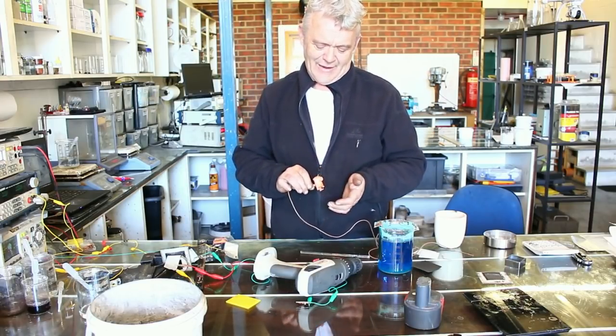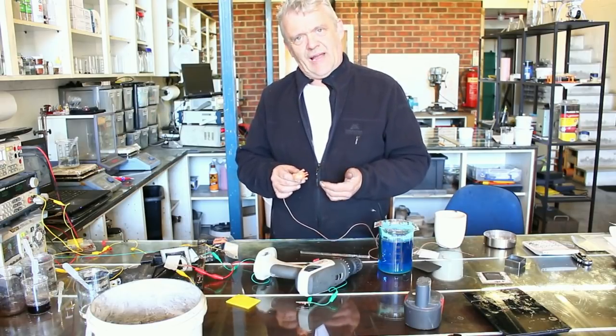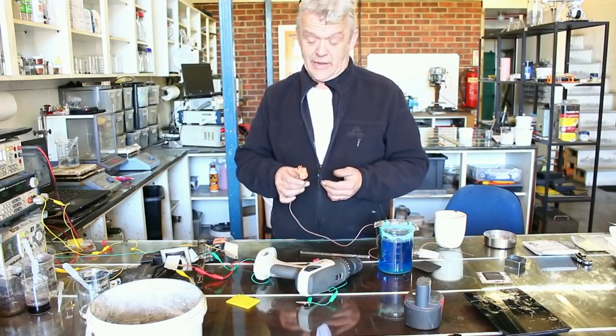Now, we put this about 50 milliamps. In order to get that 50 milliamps, we set the voltage at 0.8 of a volt and that's taken two days to do.